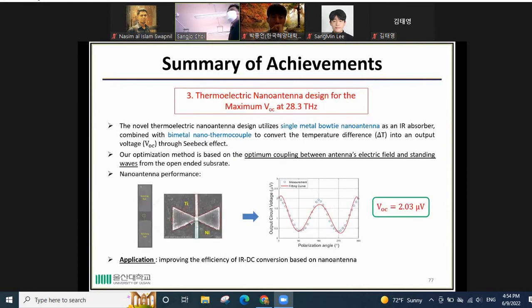And in the last, for the thermoelectric nano antenna design for the maximum VOC at 28.3 terahertz, we designed a novel thermoelectric nano antenna, utilizing a single metal bowtie nano antenna as the infrared absorber, combined with a bimetal nano thermocouple to convert the temperature difference into an output voltage through the Seebeck coefficient. Our optimization method is based on the optimum coupling between the antenna's electric field and the standing wave from the open-ended substrate. And this is the nano antenna performance.